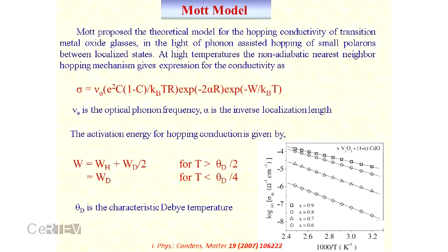This is the frequency of the phonon that is assisting conduction, and here you can see the term for the reduced valence state, because in transition metal oxide glass, when you melt, there are two types of valencies, V4+ and V5+. The electron can hop from one position to another only because of the existence of two valence states. Otherwise, the electron cannot hop. And this is the ratio of the fraction of reduced vanadium ions.